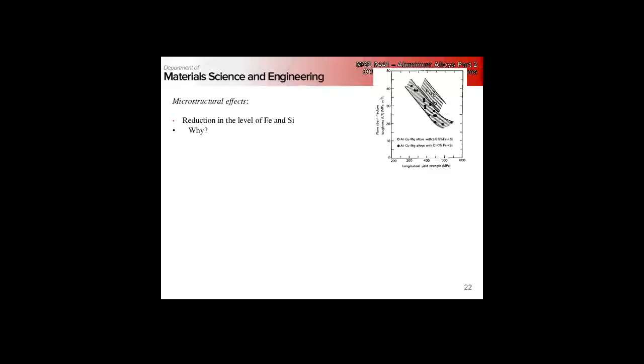So if we take a look up here, this here is the fracture toughness of the same alloy, but with greater than 1% iron and silicon impurities, and here less than 0.5%. So you can see a clear difference in the performance of these based on small changes in the concentration of iron and silicon.